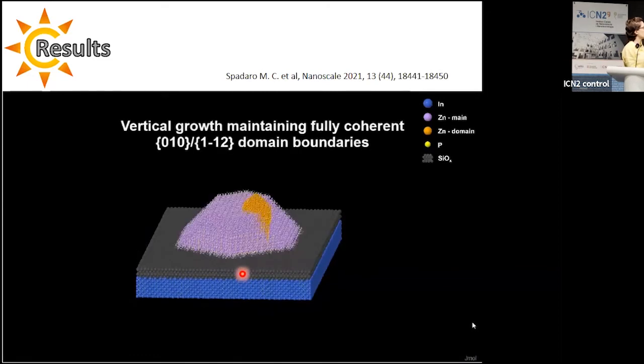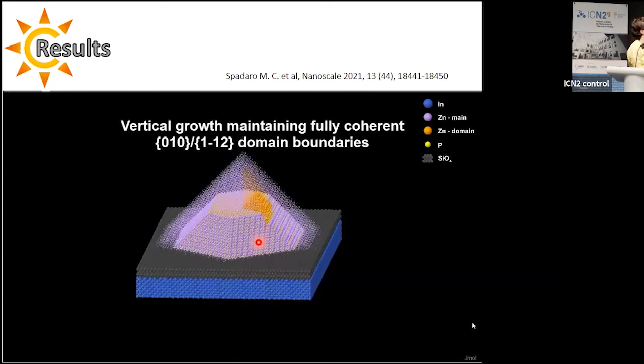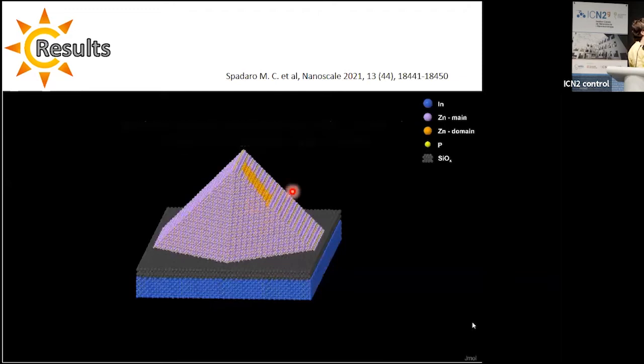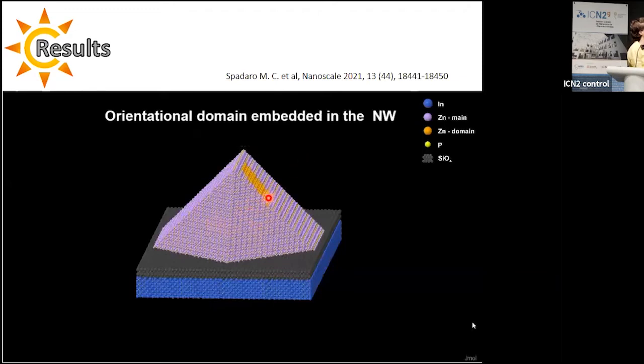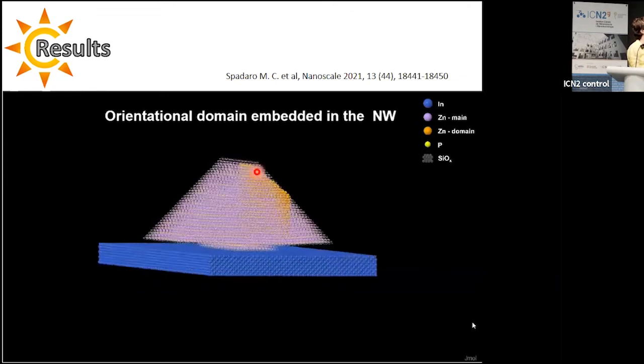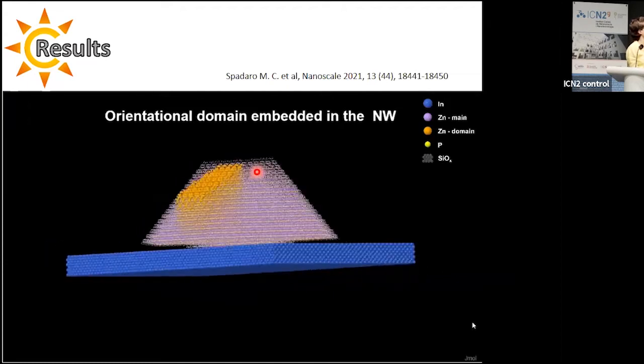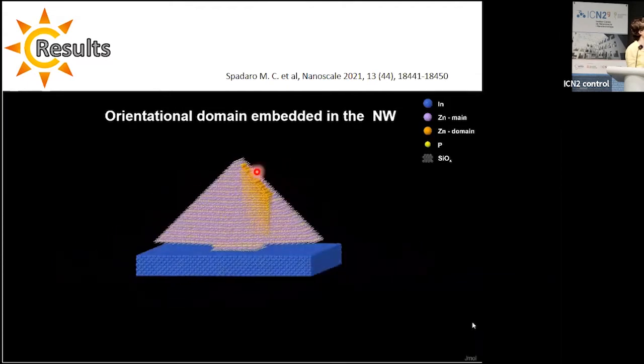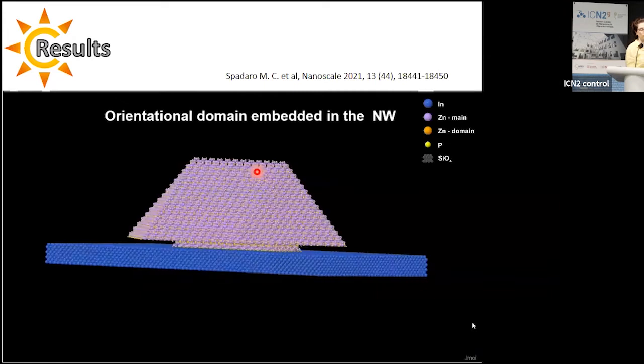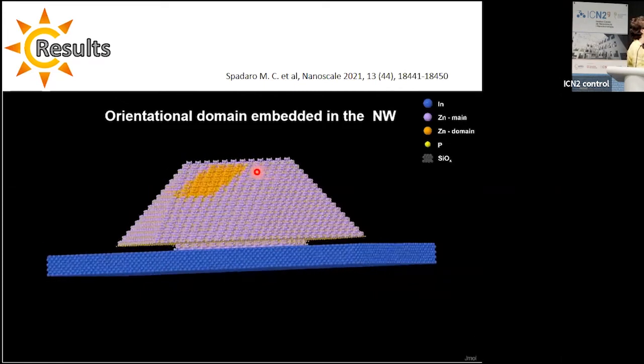It's important to notice that as soon as this type of domain appears, the rotation is kept until the end of the nanowire. Therefore, the structure doesn't go back to the original orientation, demonstrating that from a growth point of view, they are highly stable.